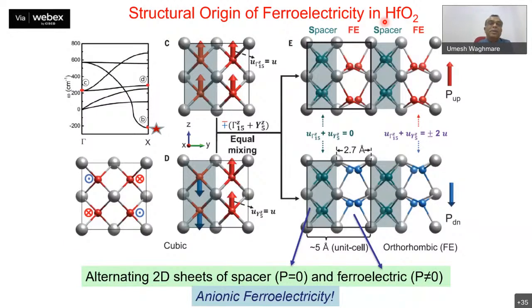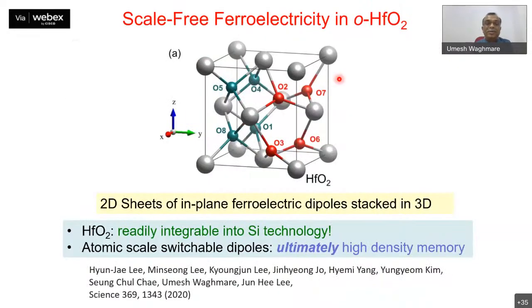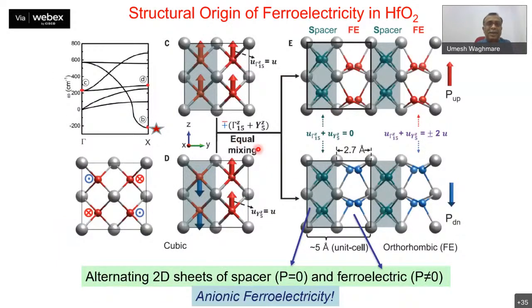So in hafnium oxide, the origin of electric dipole moment basically involves displacement of oxygen atoms in the system. And there are two types of displacements involved. One is the parallel displacement of oxygen atoms here, and the second one is anti-parallel displacement of oxygen. And what is magic about hafnium oxide is, by the way, its structure is very similar to zirconia that many of you use in jewelry. So this crystal structure is exactly the cubic zirconia structure.